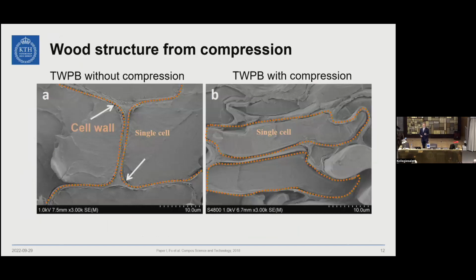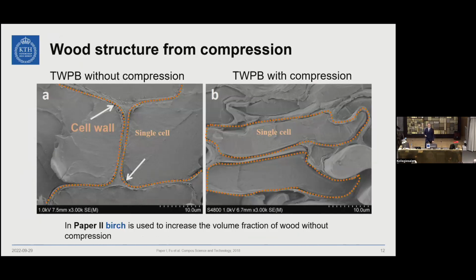When we do compression of the wood template, we are basically collapsing the cell walls. So we want to investigate another method for improving or increasing the volume fraction of reinforcement by not doing any compression. And so in paper 2, we used birch, which is a higher density wood than balsa.